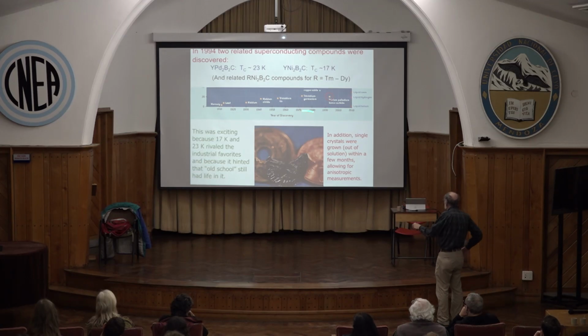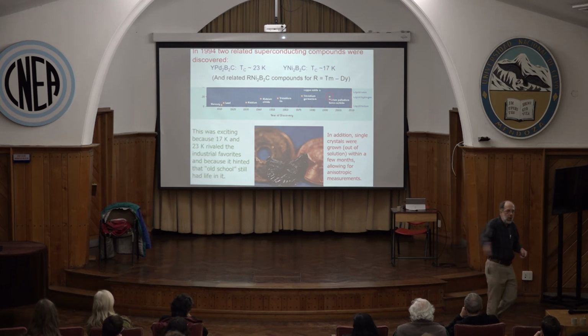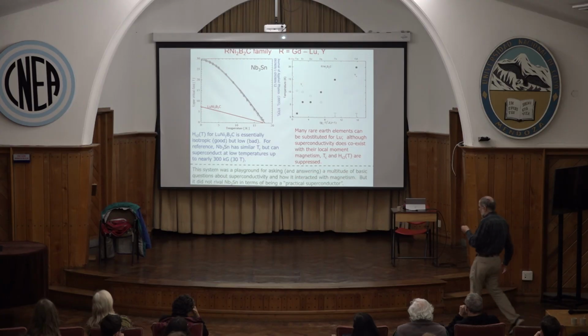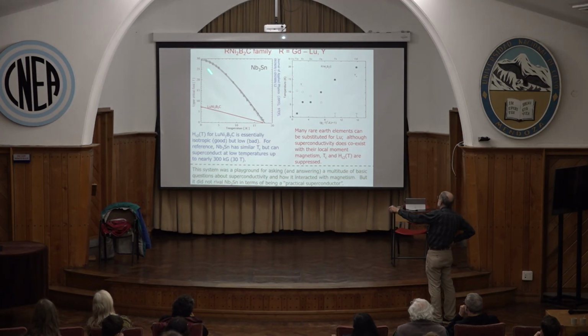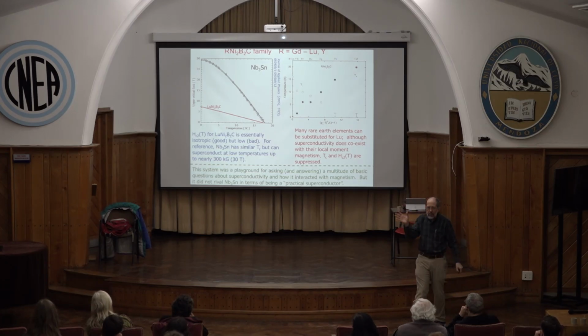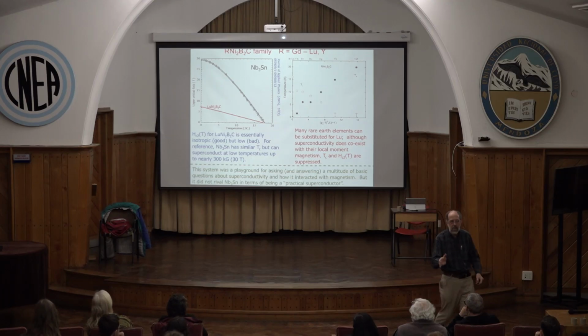So one of the bonuses was my group was able to figure out how to grow single crystals within a month or so after the discovery, so we can avoid dealing with polycrystalline results and confusion from almost the start. Now, in terms of applied physics, they're very disappointing. It has a TC almost identical to niobium 3-tin, but no matter what you do with it, you can't get HC2 much higher than 7 as opposed to 30. So these will never be a practical superconductor. In addition, lutetium is expensive, they're brittle, blah, blah, blah.